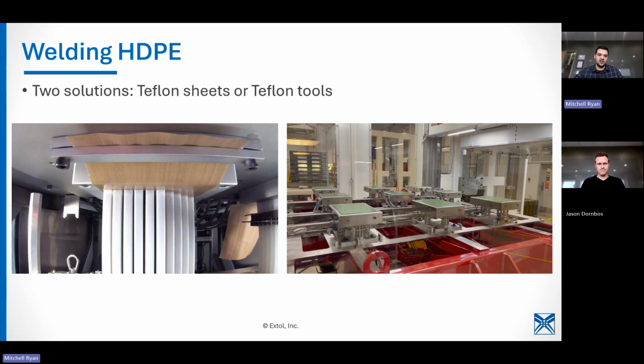We'll use Teflon sheets. We'll actually clamp those to the heated tooling and then use those to ensure that the HDPE does not stick to the hot tool. Without that coating, it would stick and string no matter the temperature that you use. Teflon sheets can be nice when, in HDPE's case, you're wearing through coatings really quickly. It's a lot less expensive to just replace a Teflon sheet than it is to have tools recoated, which is very common. It's common to have Teflon coated tools recoated. It's just a matter of how frequently you have to do that, and if that's cost prohibitive, then Teflon sheets can be a really good option.